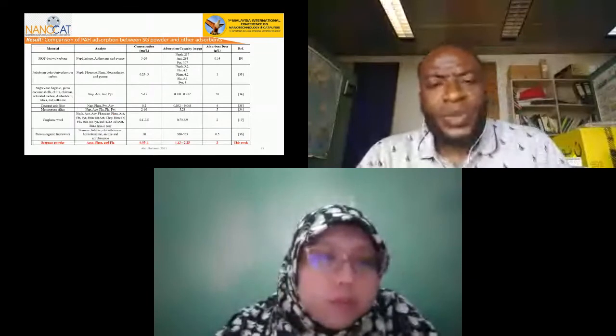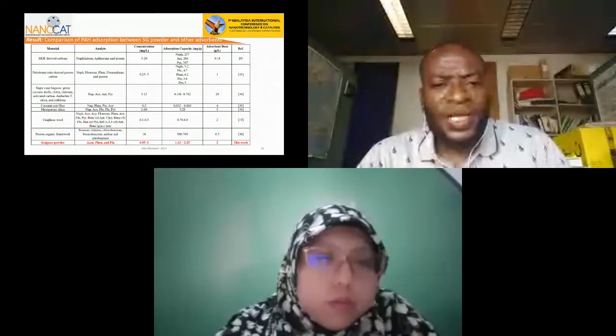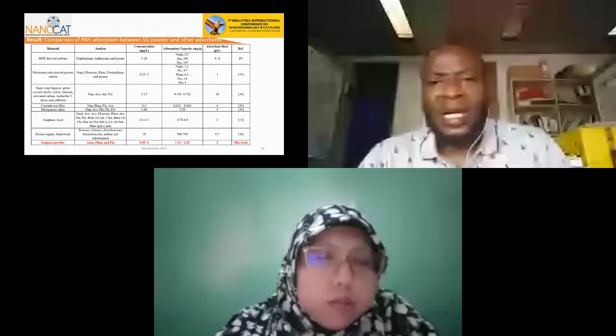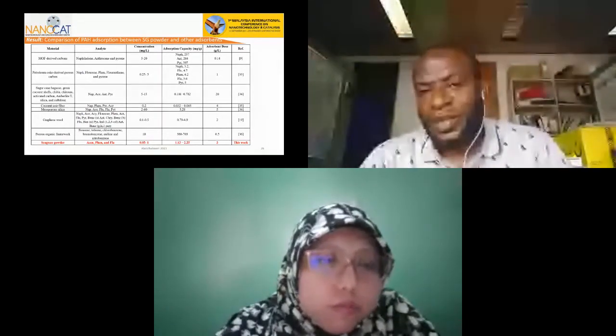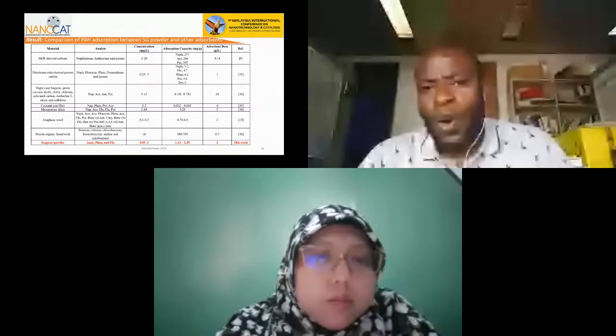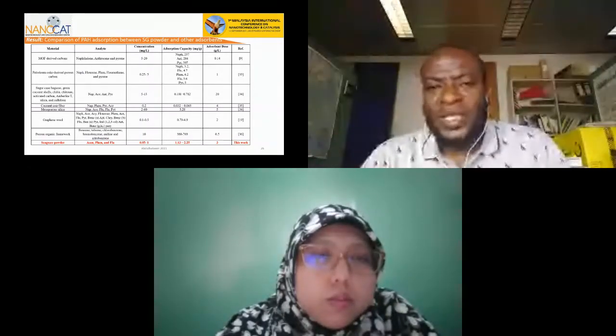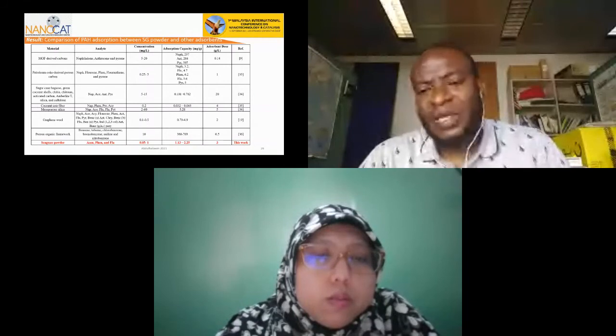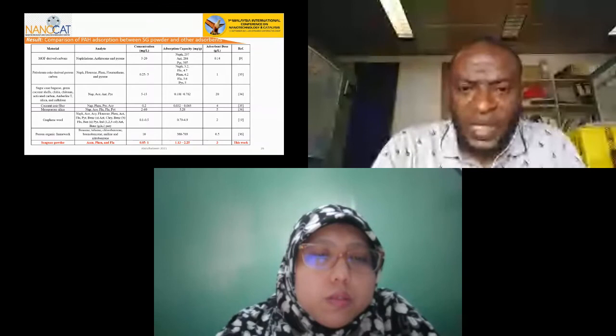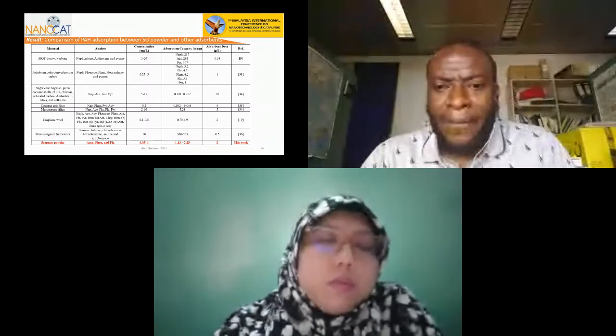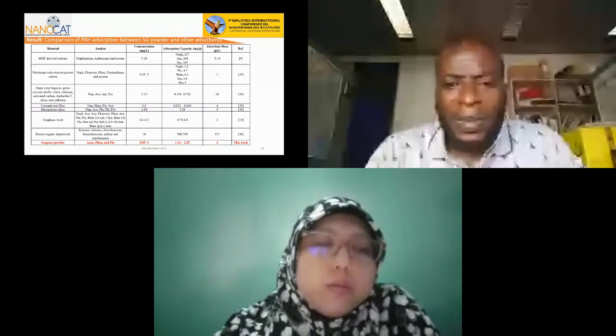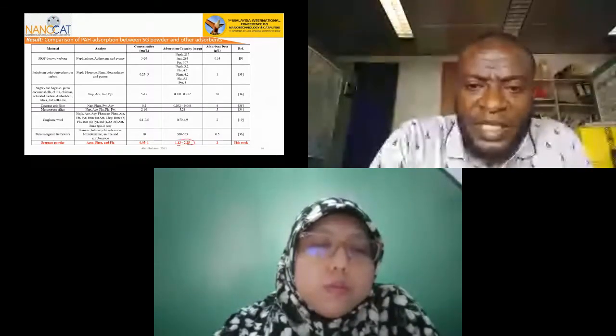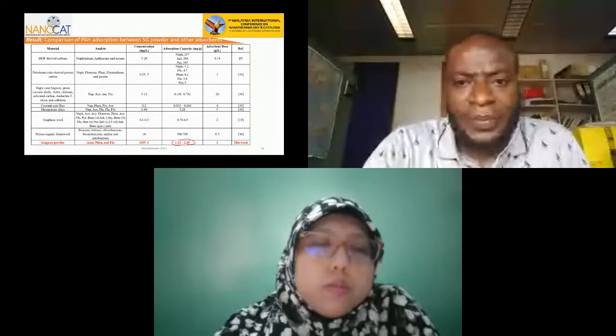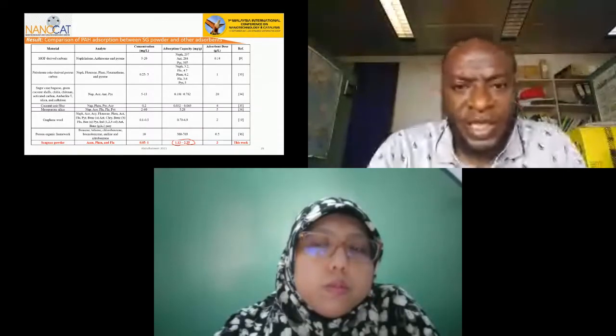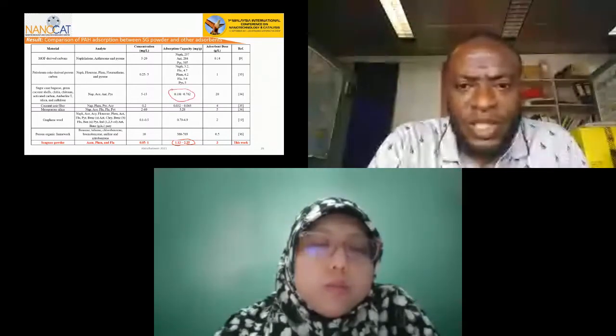And comparing this adsorbent with other reported adsorbents in the literature, we do know that this particular seagrass powder can compete favorably with many reported adsorbents in the literature. However, the fair comparison would be between this and other similar biomass. And from what we can see here, from the point of view of qe, our biomass is very good compared to many other biomass reported in the literature. It does even better than many other biomass reported in the literature.